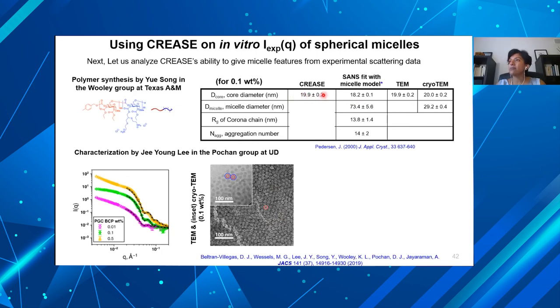What we saw is the dimension of the core, so that's that red region, matches in from CREASE, analytical model fit in SASView, microscopy, cryo-TEM. All agree really well. But you will see that the analytical model fit does not agree in the micelle diameter with cryo-TEM at all. It doesn't fit at all.